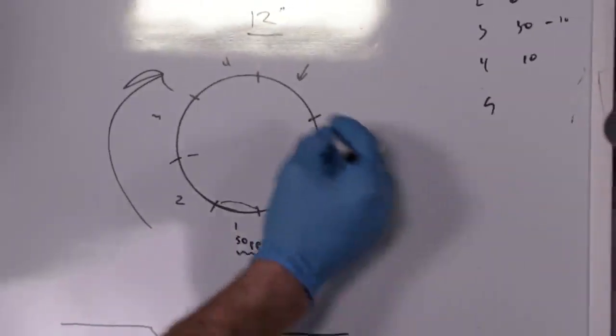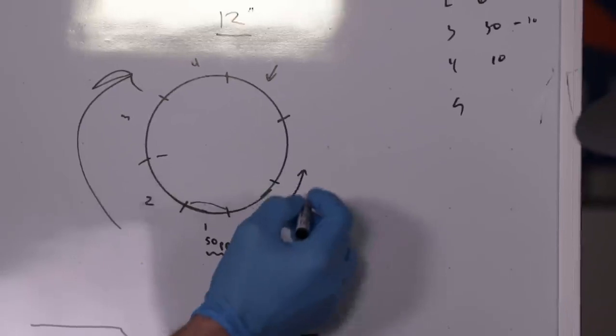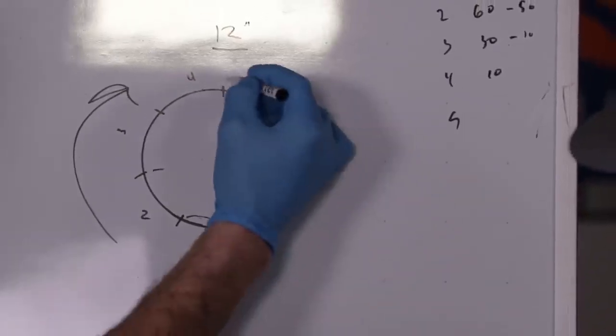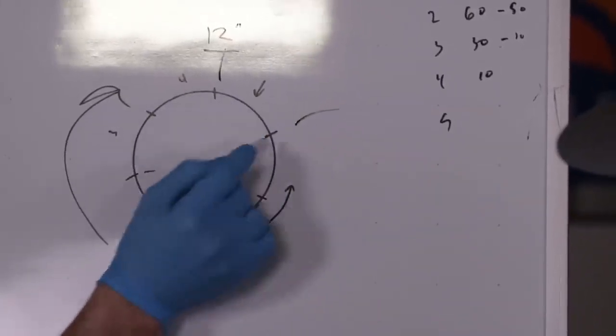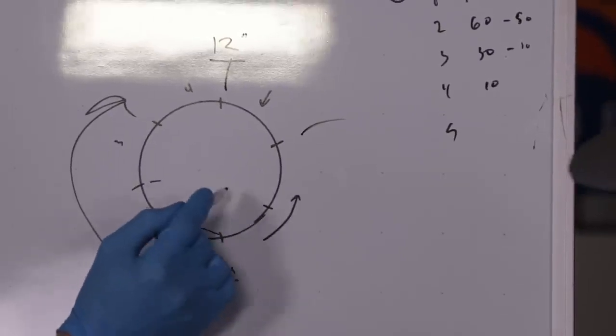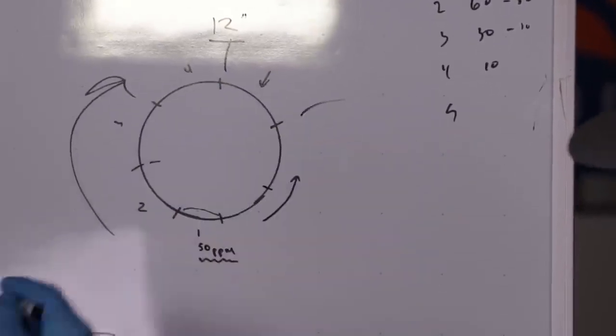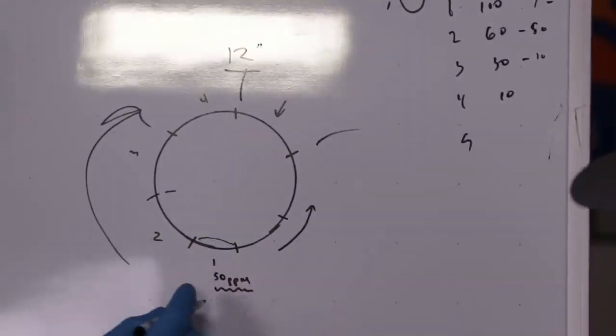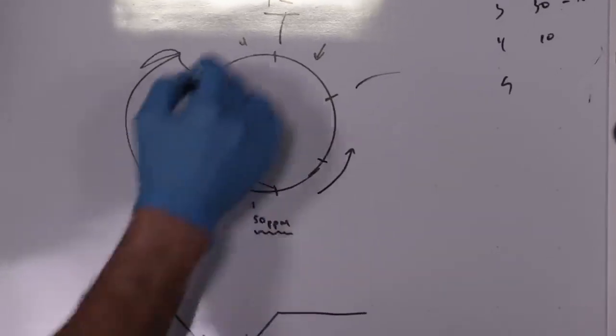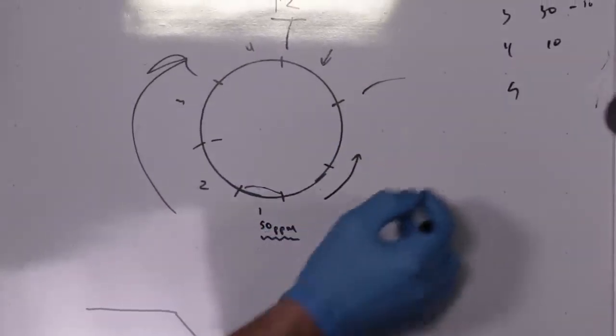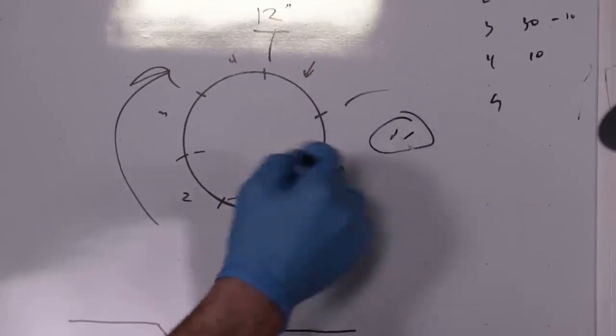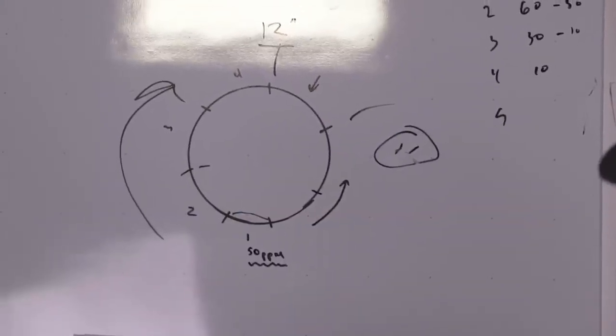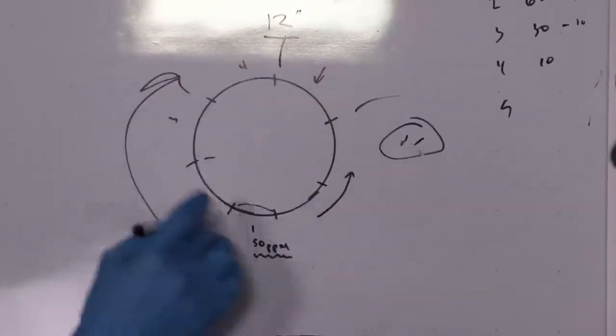But essentially, as you close up more and more of the root pass and you deposit more of the root pass into the weld, you can actually get to a point where you don't even have to tape this last section, the last quarter there, because the parts per million of oxygen is going to be very, very low. Exactly. Now, when you do close up the root pass, maybe you might even drop down to, say, 11 parts per million, 10 parts per million, etc. Very low parts per million of oxygen, because the root pass is in there.